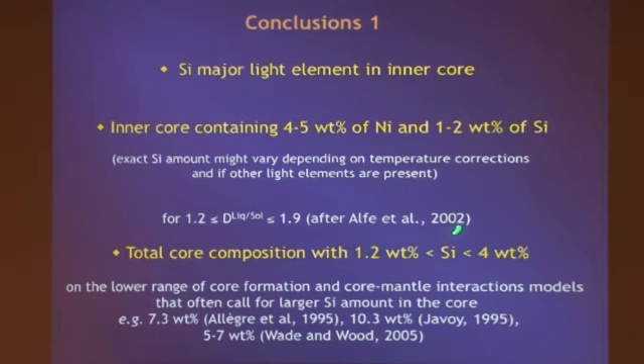However, if we take Alfè's value of the partition coefficient for silicon between liquid and solid iron, so that we can estimate the silicon amount in the outer core and then a total core amount of silicon, we end up with a total core composition with a silicon amount ranging between 1.2 and 4 weight%, which is on the lower range of core formation and core interaction models that typically call for larger amounts of silicon in the core. Here the bottom message is we cannot have 10 weight% of silicon in the core. That would result in too high a sound velocity with respect to the seismic observation.